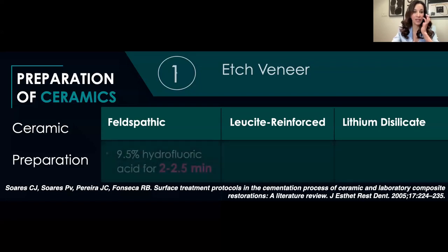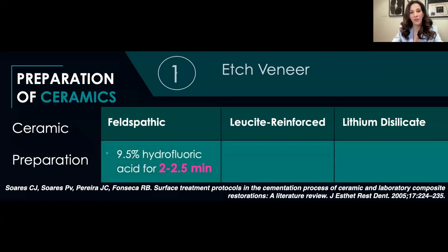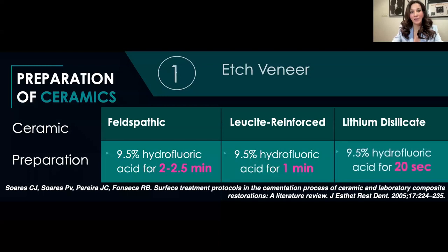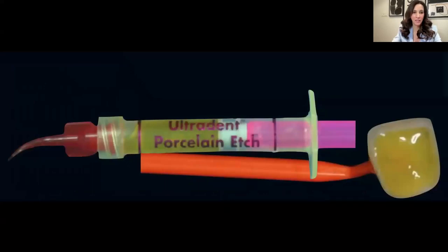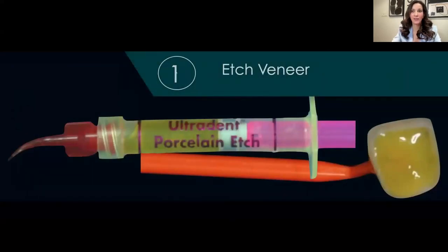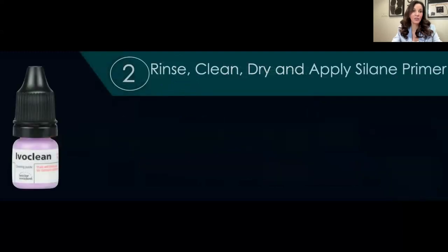If you're using a feldspathic, you're going to be etching with 9.5% hydrofluoric acid for 2 to 2.5 minutes. Leucite reinforced for 1 minute, and lithium disilicate for only 20 seconds. The idea is that the veneer is etched, and you have a nicely etched surface to bond to. Now, I personally like to etch my veneers chairside as opposed to having my lab etch it for me, because as soon as you try in your veneer, you're contaminating it. If you choose to have your lab etch the veneer for you, that's fine. But then you need to use a material like Ivoclean to clean off the surface of the veneer.